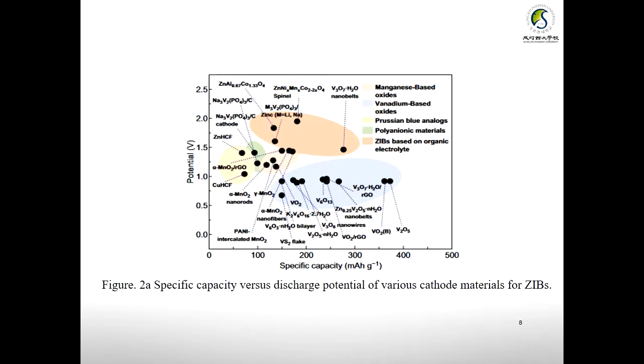The specific capacity versus discharge potential of various cathode materials for zinc-ion batteries, which I presented here, shows that majorly for zinc-ion batteries they are using two kinds of material. One is manganese-based material and the other is vanadium-based material. In the case of manganese-based material, it shows a lower specific capacity, but the potential is much higher than the vanadium-based materials. Whereas vanadium-based material can be stable at around 1 to 1.5 volt potential. With an increased specific capacity, we can attain around 400 milliampere hour per gram.